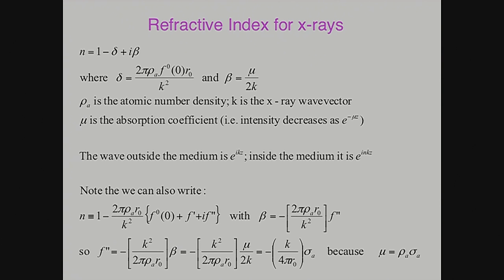So you imagine you have a wave function which is e to the i k r, right? If k has an imaginary quantity in it, it will come out as i times i, which is minus, and will have a damping because it'll be exponentially damped. And that's done because with X-rays you have to include the absorption term, the damping term. But other than that, the two come out to be exactly similar, the neutron and the X-ray case, and the magnitudes are quite similar, within a factor of 10 at least.